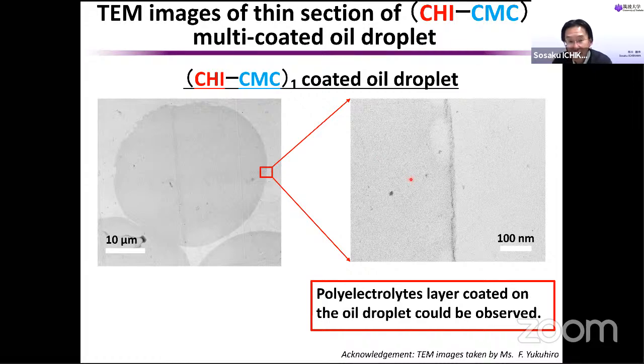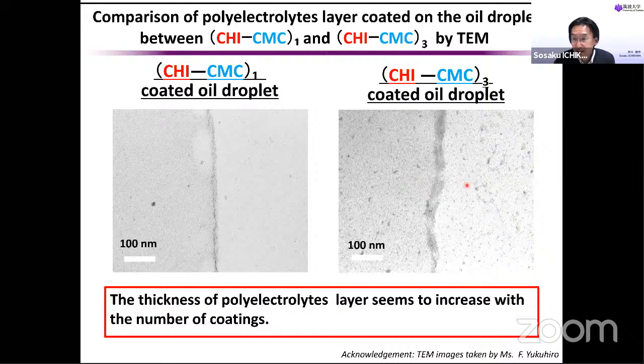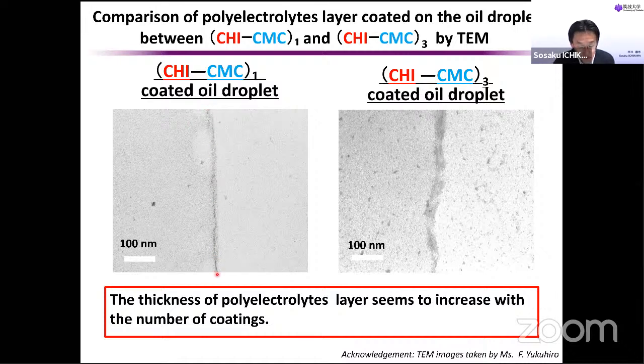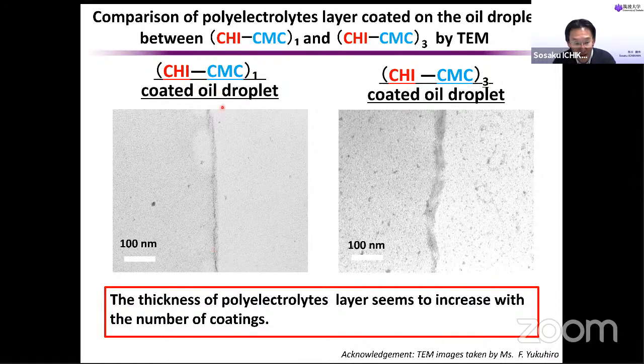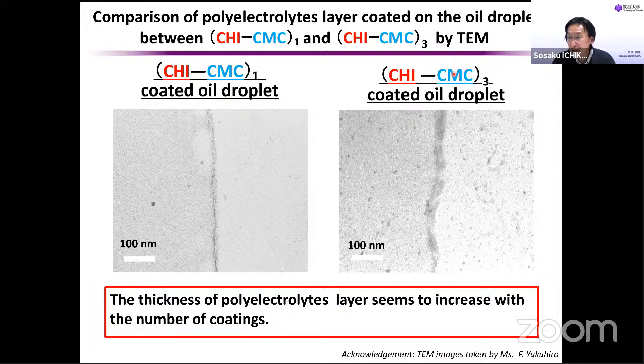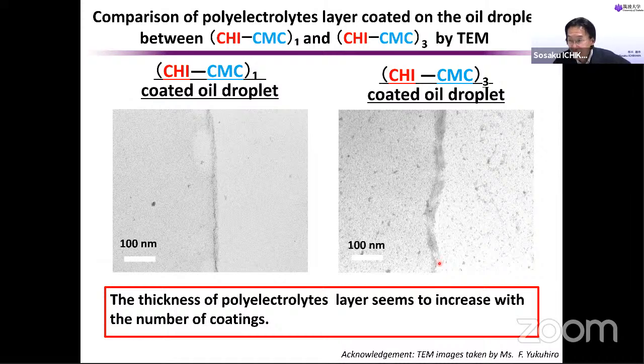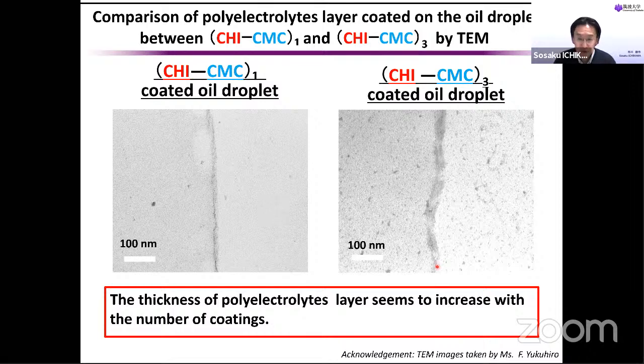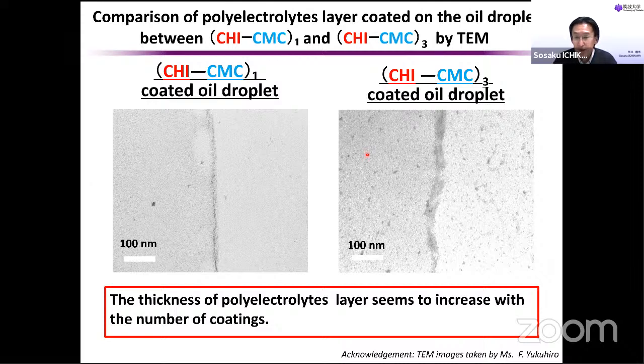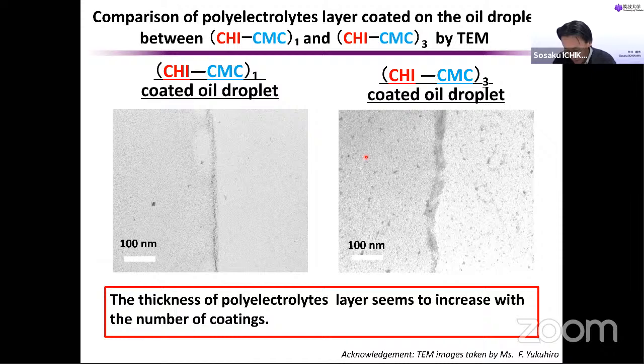But in the next slide, we can see the six-layer coating. You can compare the thickness of the layers. Here is two layers, chitosan and CMC, two layers thickness. This is chitosan and CMC, six layers thickness. So you can see the thickness of the polyelectrolyte layer seems to increase with the number of coatings. So it means it's possible to control the release of ingredients in the oil droplet, and also to control the stability of the oil droplet.